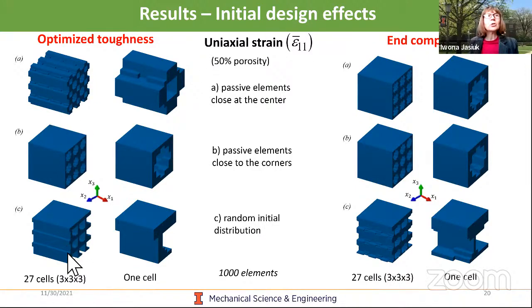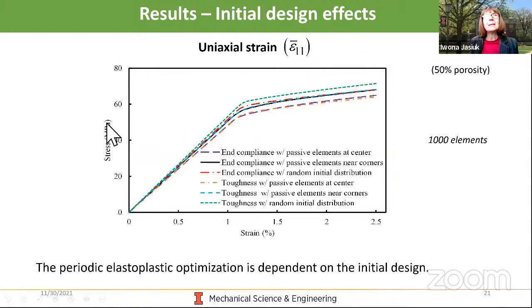The first column shows the 27 cells for a 3 by 3 by 3 configuration. One can see closer detail of each of the unit cells in the images in the second column. The first row represents passive elements assigned close to the center, and then in the second row, passive elements close to the corners, and in the third case, a random initial distribution, and similarly for end compliance. So one can see that there are differences in designs due to these initial configurations, and this is also seen in the stress strain curves for the 6 cases as summarized here.